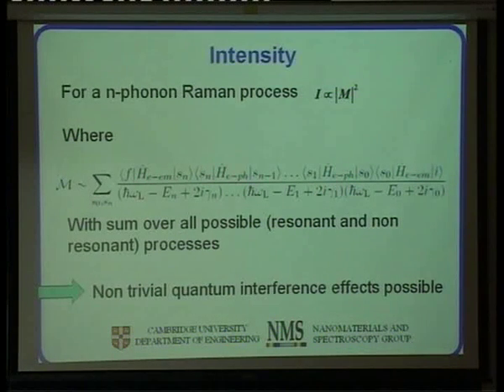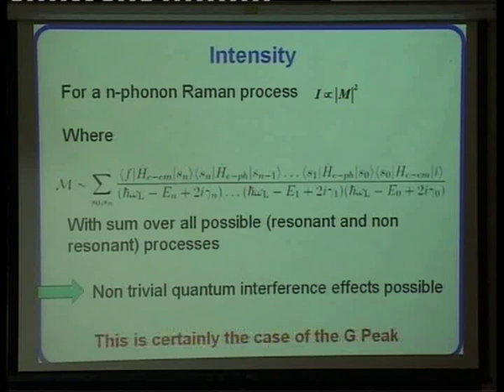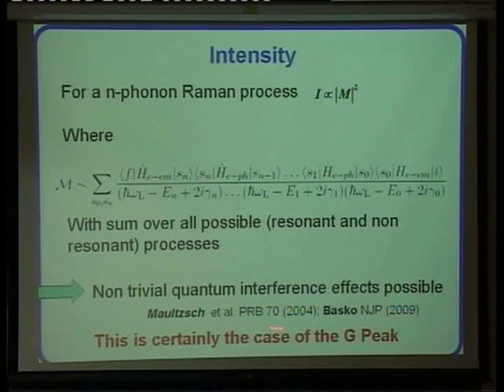But of course this is wrong, and if you did want to do the calculation properly, you would have quantum interference effects, and quite surprisingly, nobody considered this until 1 or 2 years ago in the case of Raman spectroscopy. And especially nobody considered it in the case of the G peak, which seemed to be a very simple and straightforward situation. In fact, there was a paper in 2004 by Maultzsch and colleagues where they suggested you should look at quantum interference, but they themselves did not look at it, and nobody else cared to read the paper, or at least that part, after 2004. The first decent paper on the subject, purely theoretical, is in New Journal of Physics by Dennis Basko in 2009. So after 2009, people started thinking a little bit more about this.